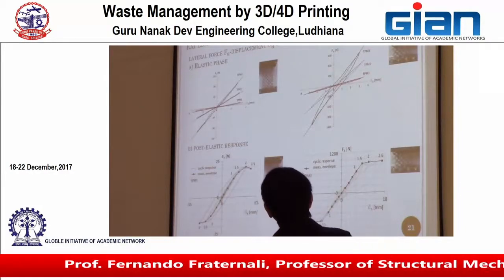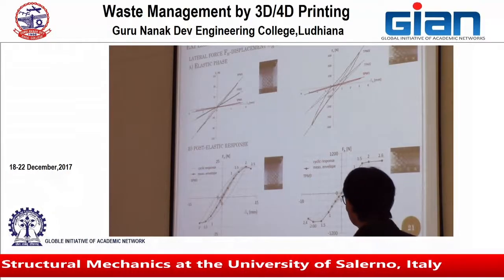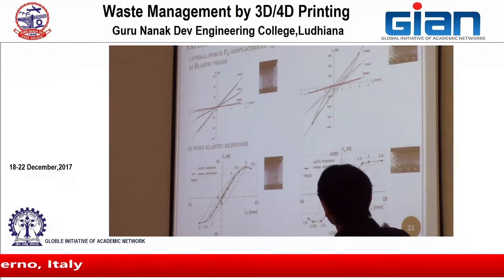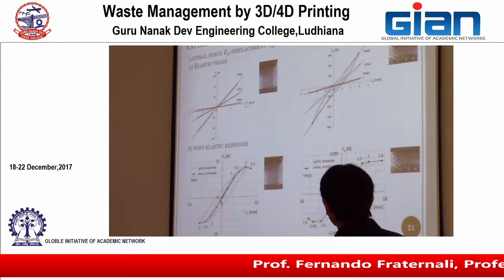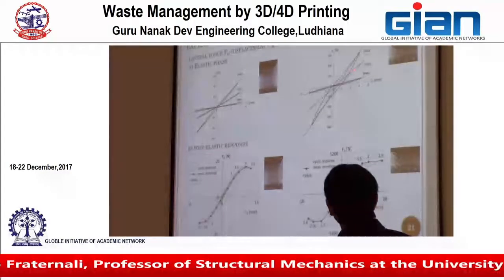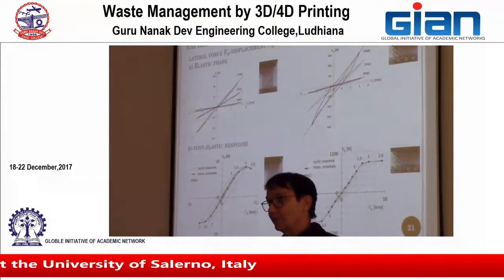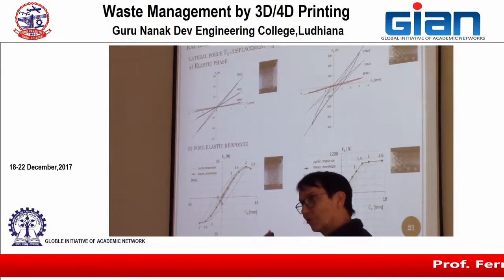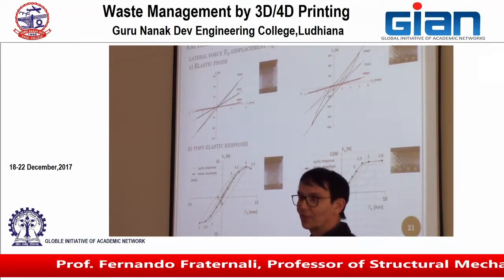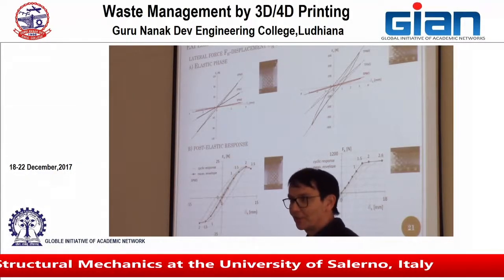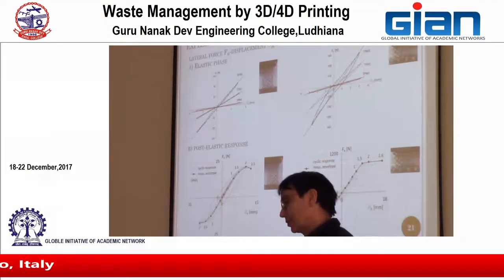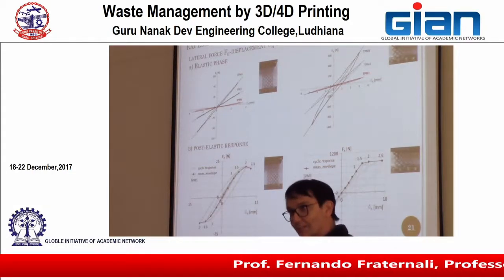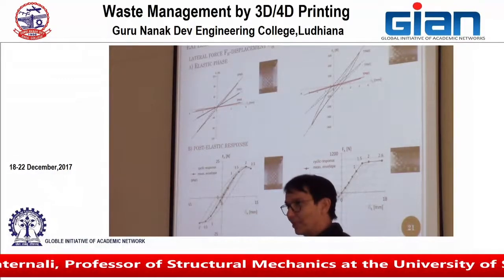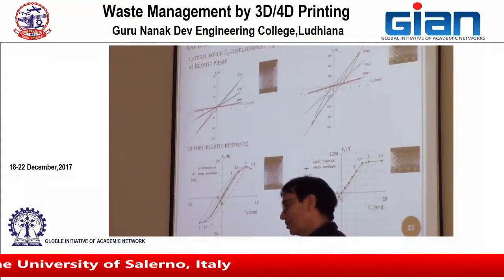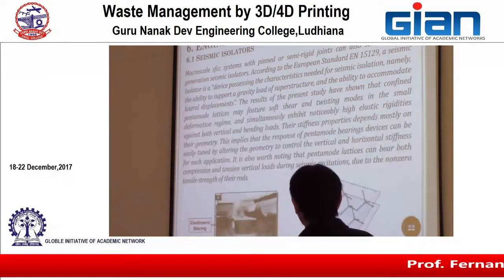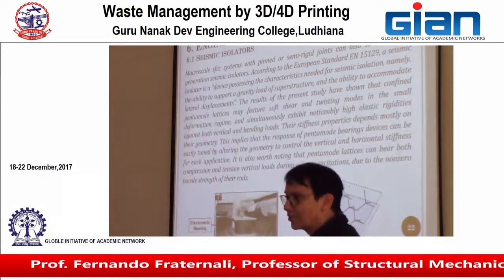And then we built physical models by 3D printing, and we ran some tests for different geometries, and we observed quite good comparison between theory and experiments. We observed also some dissipation properties. This is also a good dissipative system, because you have several sources of dissipation. What are the sources of dissipation? Friction at the nodes. You have also plasticity of the members. The members, when displaced, go plastic. So you can dissipate energy with plastic deformation. So we have proposed this as a seismic isolator. We have patented this application, which was our idea.